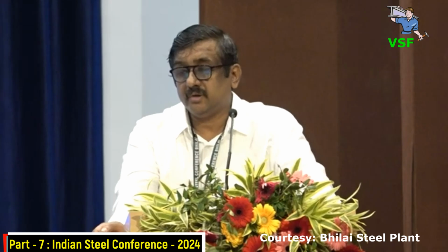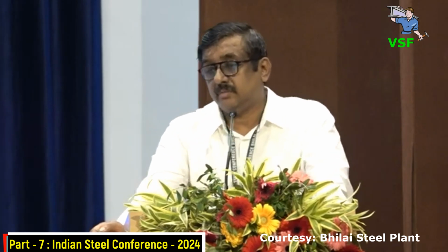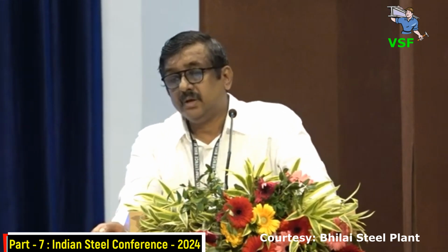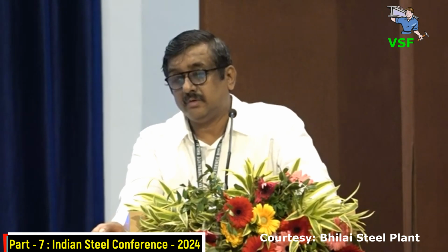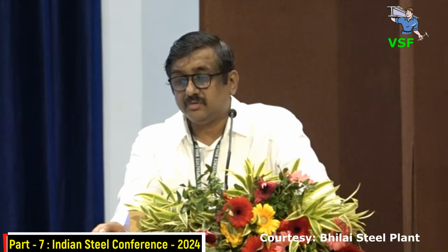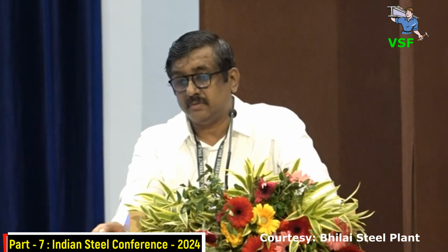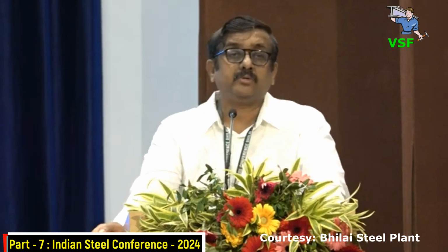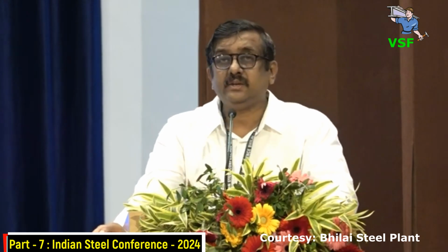The hot air volume is around 50 to 60 thousand Nm³ per hour. Temperatures will reach more than 200 degrees centigrade. Water quantity to be used is around 30 tons per hour, and hot water temperature will come to around 80 to 90 degrees.